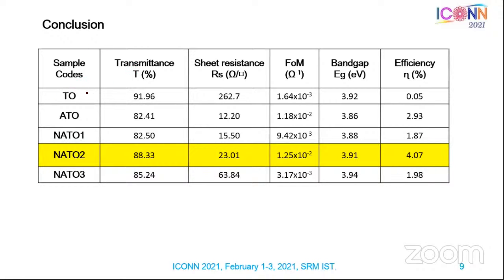If you observe the transmittance in all the films, tin oxide shows high transmittance, but in the case of sheet resistance, it is about 262.7 ohms. So when we calculate the figure of merit from these two values, we have a very low figure of merit. For ATO, transparency decreased, but sheet resistance also decreased. So that's why it is showing nearly 3 efficiency.